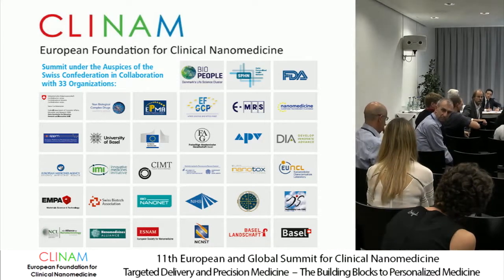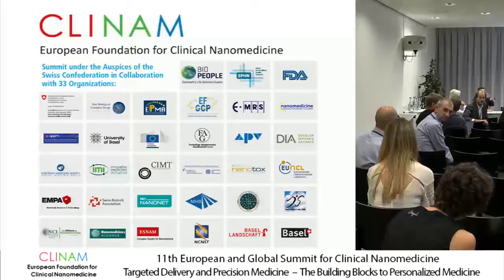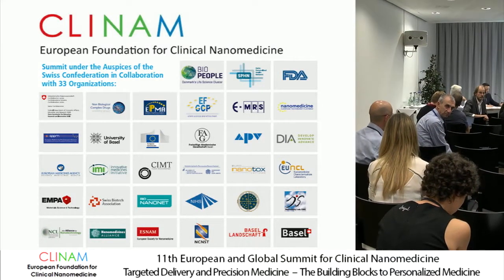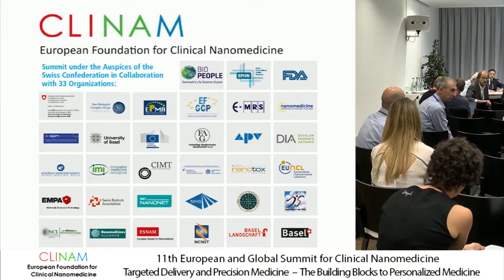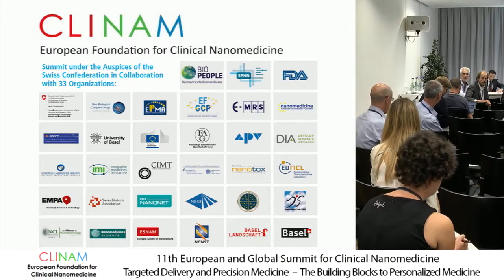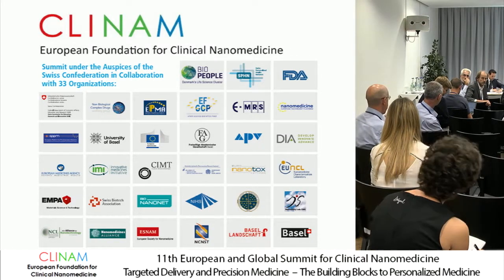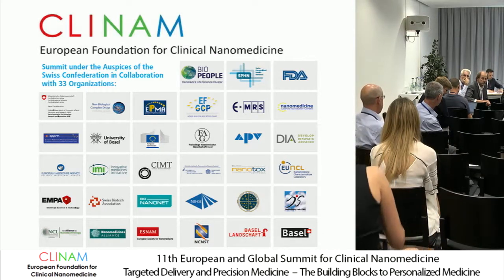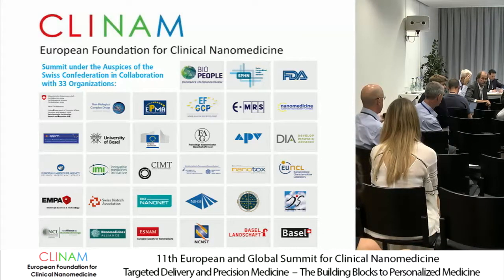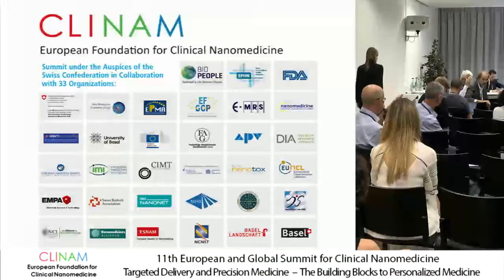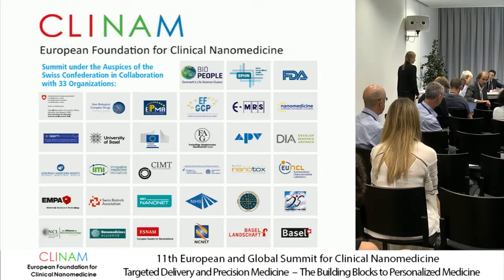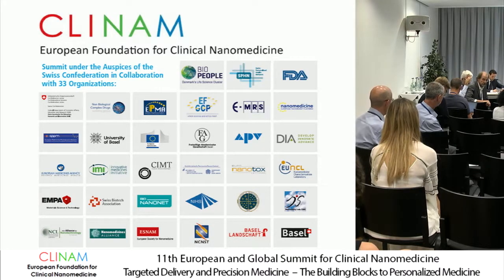But if I can go to what Adriele was saying about how you're going to measure the size of your particle in a complex media, let's say in plasma, in the presence of protein, it really depends material to material. And in our experience, we are used to especially metallic, high-density nanoparticles, and we have had a lot of success with different techniques presented this morning, like centrifugal particle sedimentation, or a very expensive one, analytical ultracentrifugation.